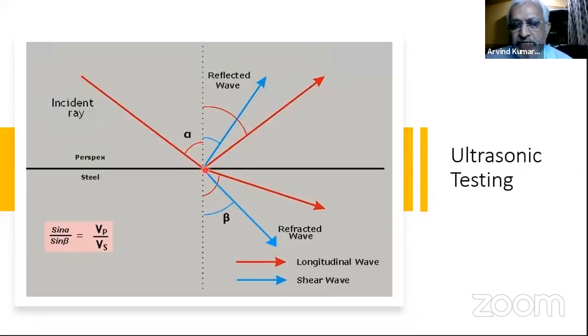Now at the interface, it is going to split into a refracted longitudinal wave and a refracted shear wave. And there will be a reflected longitudinal wave and a reflected shear wave. We are not worried about this. Now we have two waves in the material. We cannot do any testing because there are two waves and each has a different velocity. The longitudinal wave in steel travels at about 6,000 meters per second, whereas the shear wave is about 3,200 meters per second.